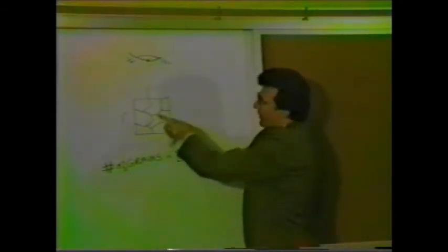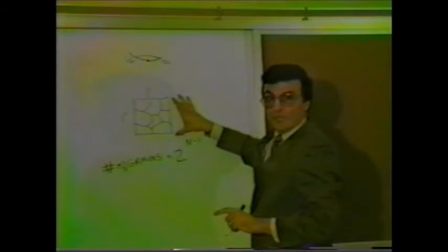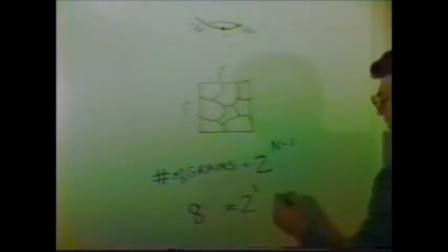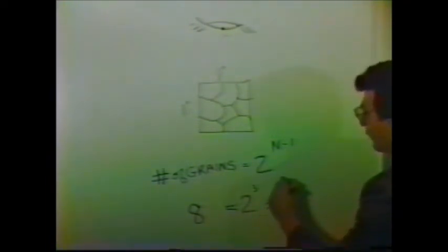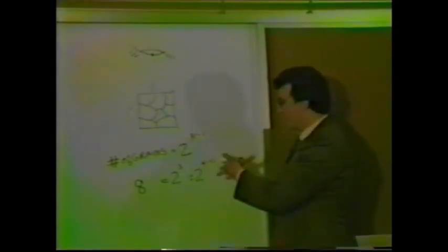Let's say, for example, that you counted an average of 8 grains in a 1 square inch area viewed at 100x magnification. So if you had 8 grains here, that is equal to 2 to the something power. And that's 2 cubed, 2 to the 3rd power. Now, something minus 1 has to equal 3. So this would be 2 to the 4 minus 1, or 2 to the 3rd power. In this case, if you found an average of 8 grains in 1 square inch, the grain size number n would be 4. Now, if there were more grains, there would be 2 to a larger number, and then the grain size number would be a higher number.